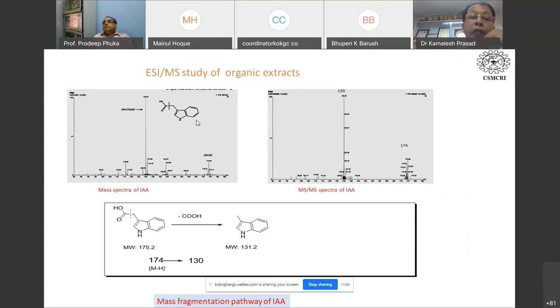So here you get the molecular weight. The molecular weight of indoleacetic acid is 175, and here we are getting a molecular ion peak around 174. We get 174, not 175, because in negative mode you get the molecular weight as M minus H, one hydrogen less than the molecular ion. So M minus H, and then you get a daughter ion peak. This daughter ion peak is characteristic of any molecule.